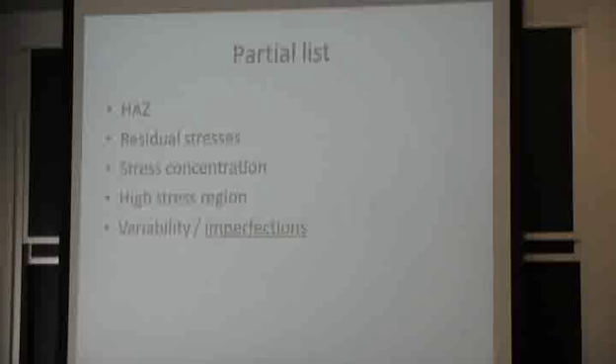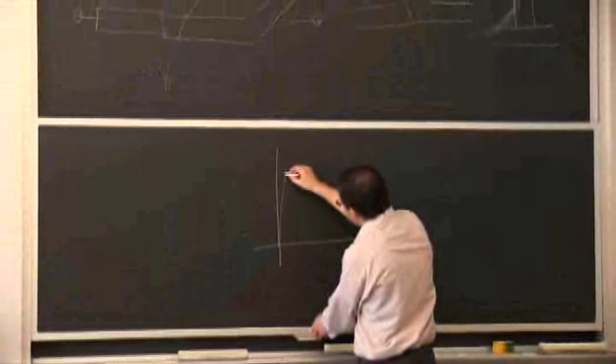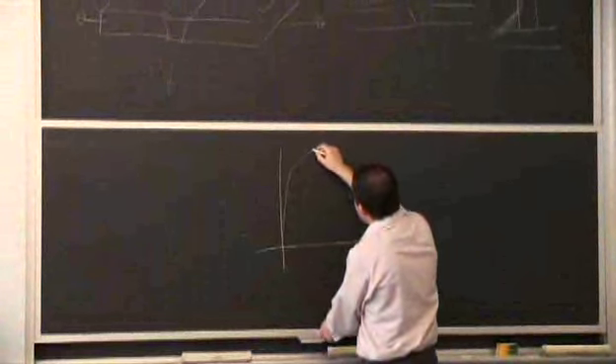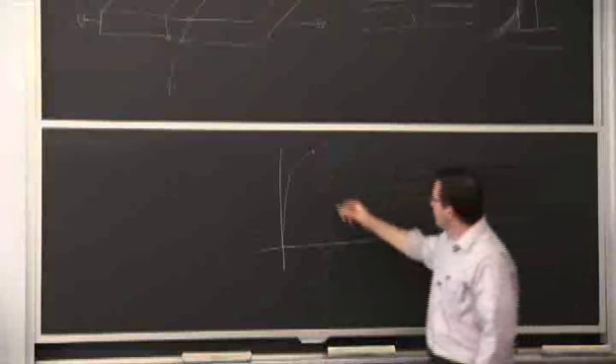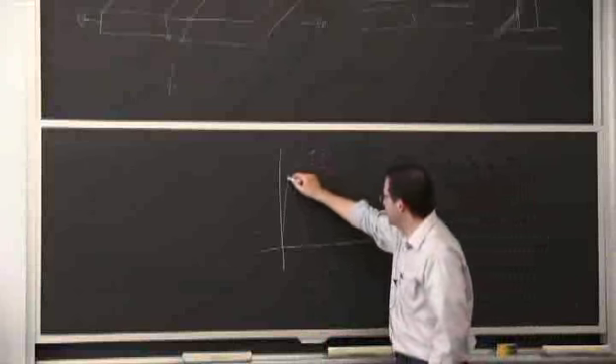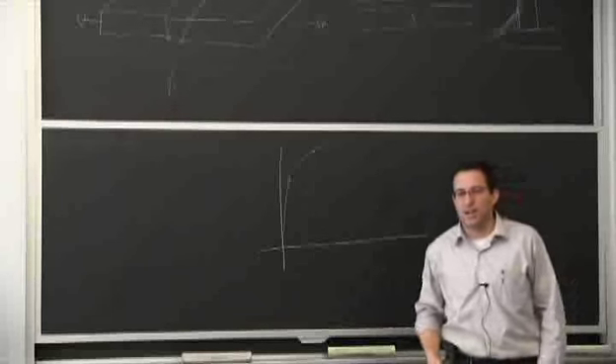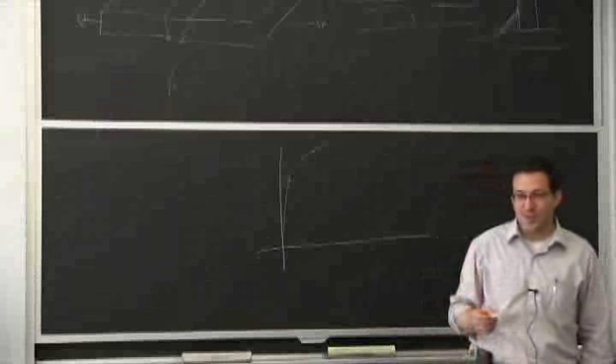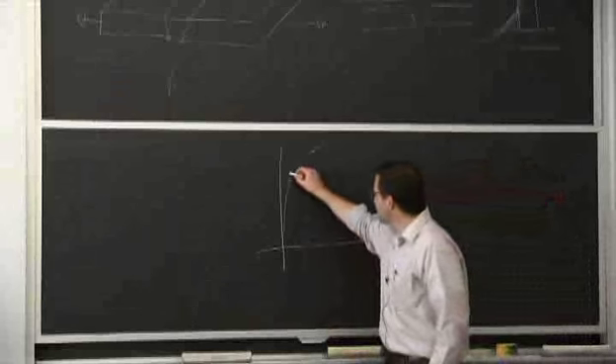If you remember, we had this 4-inch thick plate of aluminum that we said we were going to stretch to relieve some of the residual stresses. And the idea was, whatever the stress profile is, if you're going to strain it 1% plastically, it doesn't matter anymore. So it's this idea, if we go back to the stress strain curve, residual stresses in the weld, say we're talking here, and then if in service we're looking at an overload where we will have ductility, we're going to load it up here, it doesn't matter where you started. You'll still have the same strength. Now, this is assuming you have ductility, because we're really starting to yield a weld.